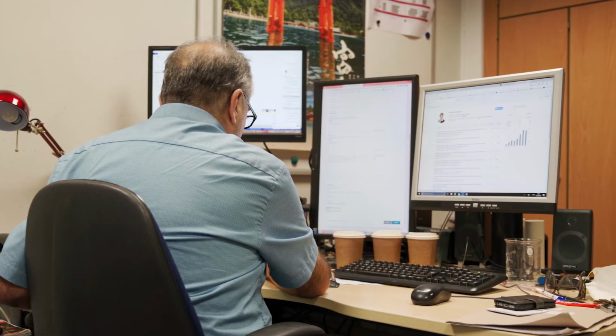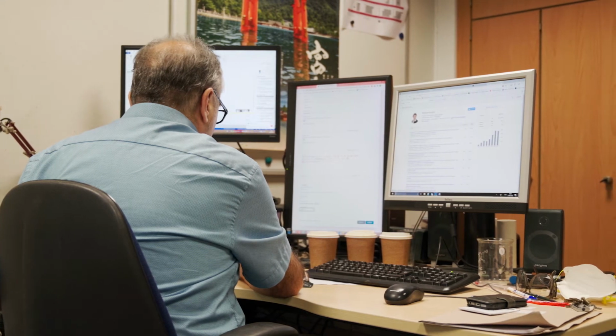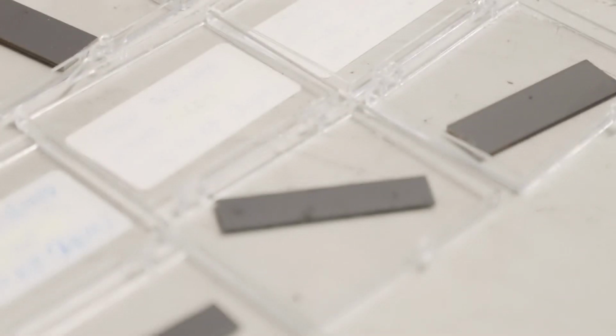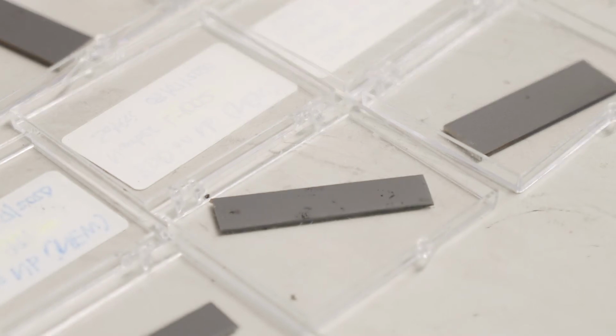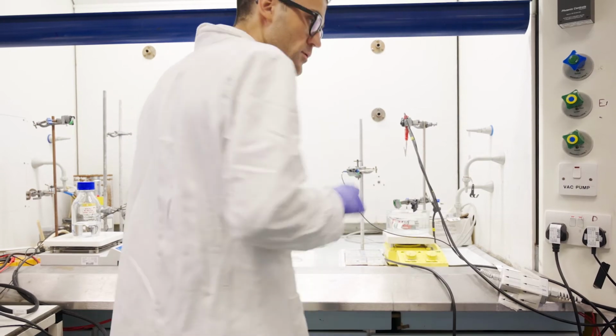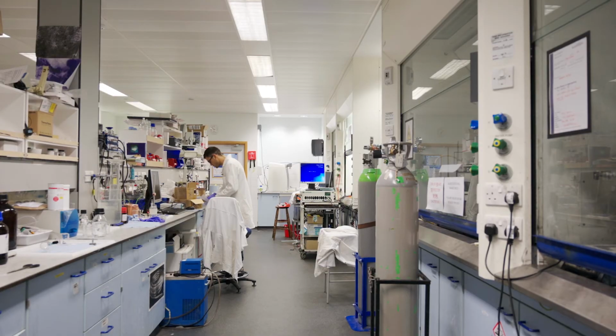On the other hand, SOTON is working on the anode side in the other part of the electrochemical cell, and we have proposed a boron-doped diamond electrode. We had a breakthrough with especially the hydrogen peroxide production, and we found that the BDD performed extremely well. SOTON has done a fantastic job in terms of screening the different types.